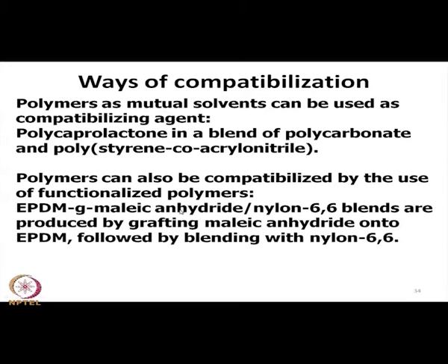So, here we can say this EPDM has been functionalized by grafting maleic anhydride, so that it becomes miscible with nylon 6,6. Before such functionalization, EPDM was not miscible with nylon 6,6. So, the interface adhesion, interface bonding of these two component polymers EPDM and nylon 6,6 could be improved by grafting maleic anhydride on EPDM.